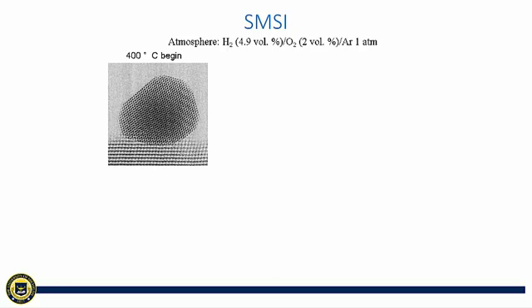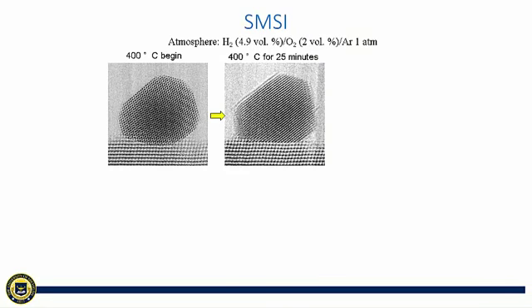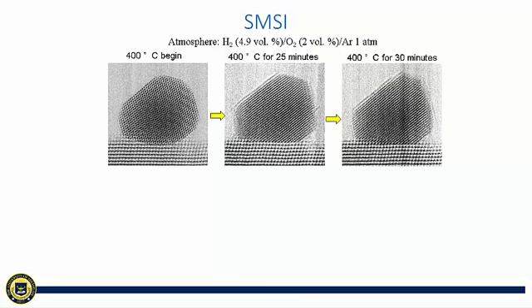And next I'm going to show the shape change induced by the formation of the overlayer. This image was taken under 4.9% of hydrogen balanced with 2% of oxygen. The image was taken at 400 C. After 25 minutes at this temperature, we can start to see the formation of the overlayer, accompanied by the shape change. And if we wait for a longer time, we can even see the aspect ratio change of the particle. It becomes taller.